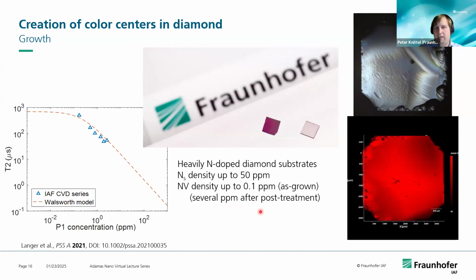And the spin coherence time of these diamonds is mainly determined by the surrounding substitutional nitrogen, which is also called P1 center. And this is shown in this plot here. So depending on the amount of P1 centers, you actually decrease your spin dephasing time. But what this actually shows is that there is a theoretical model developed in the Walsworth group, and you can grow these diamonds and you reach the theoretical limits with this growth approach by CVD.